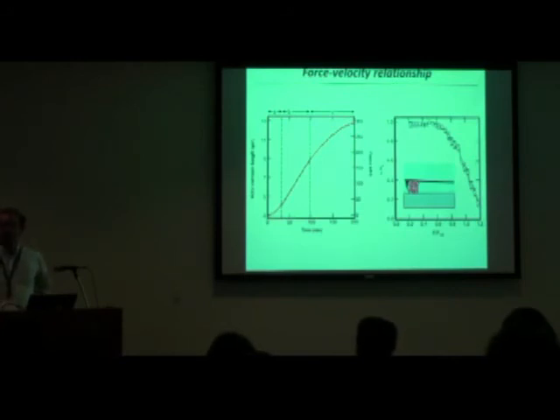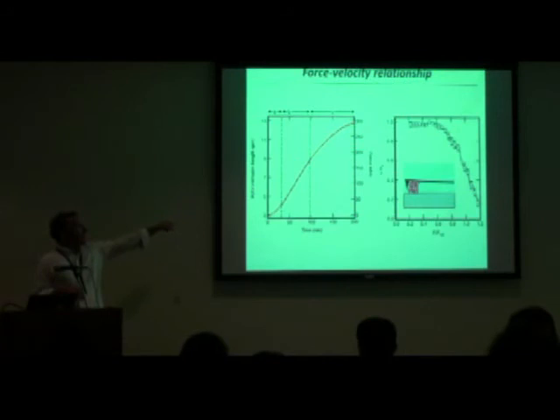So a way to characterize how dynamic networks work, or how motor molecules work, is to measure a force velocity. That's kind of like, for your car, a torque RPM curve. You want to know how many RPM do I need to go to in order to get a certain torque. Well, it's similar here. How much force can be resisted for a given growth rate. And to measure that, you can do that easily with a force microscope like this. Simply allow the network to grow. You're measuring rate of displacement, and you're also measuring deflection, which gives you force. So you've got force and velocity directly from a growth curve.